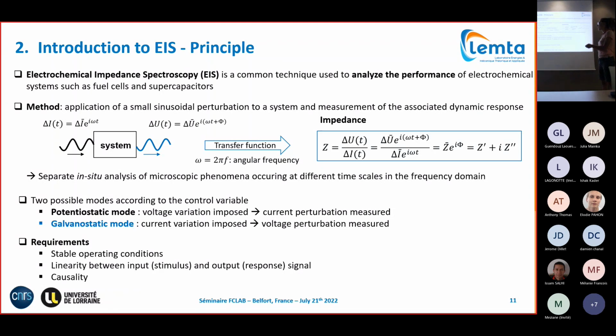So, for example, if you apply a current perturbation, you measure a voltage perturbation for a given frequency, and it allows you to identify the transfer function, meaning the impedance, which is a complex number depending on the frequency. The main advantage of this technique is that it allows you to consider separately the frequency domain, which separates different phenomena that have different characteristic time scales, and to analyze them separately in the frequency domain.